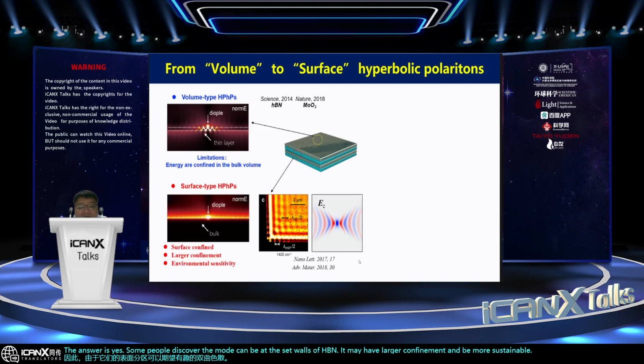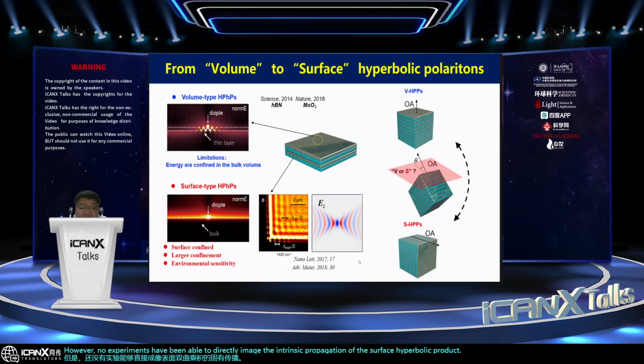However, no experiments have been able to directly image the intrinsic propagation of the surface hyperbolic polaritons. So actually, we can try to understand the volume and the surface type of hyperbolic polaritons on the plane with different optical axis orientation. If the OA is perpendicular to the plane, it may support volume modes, and if the OA is in plane, it may support surface modes.